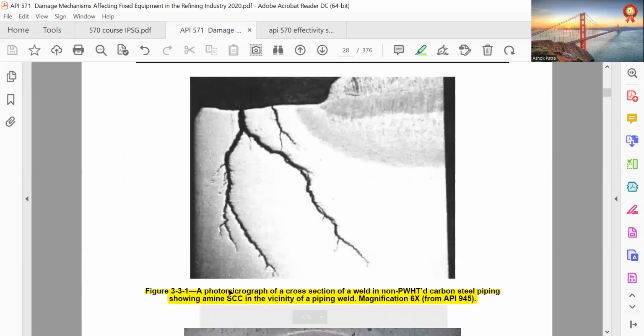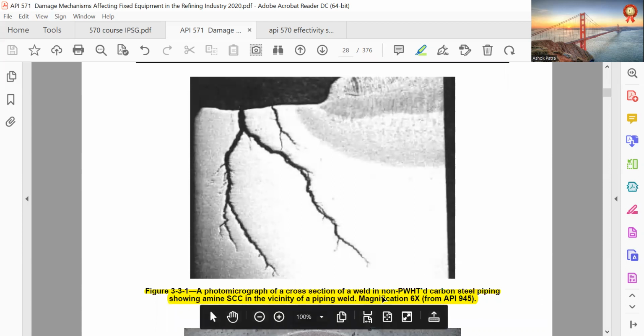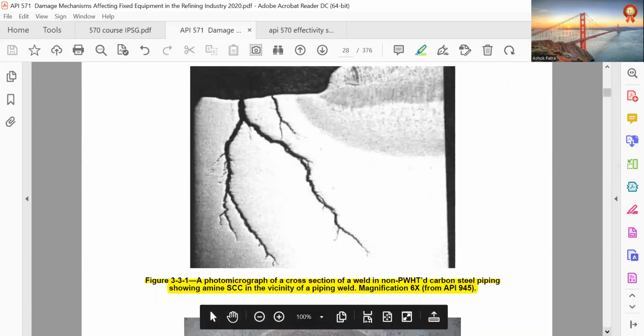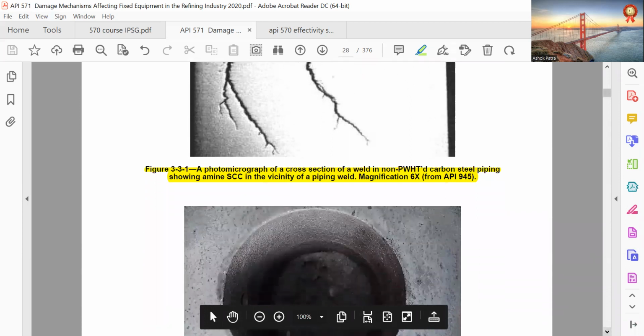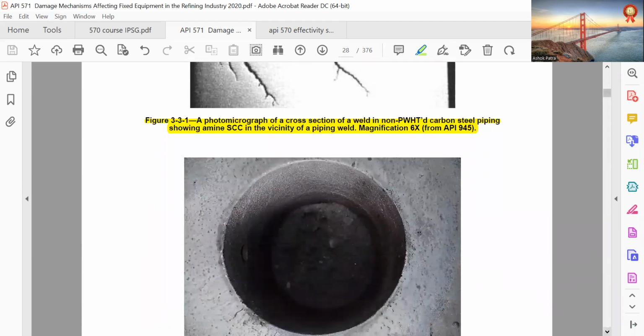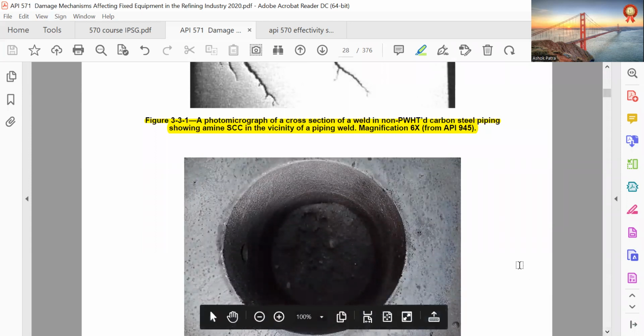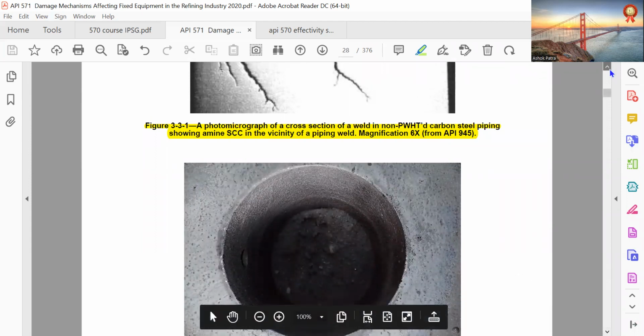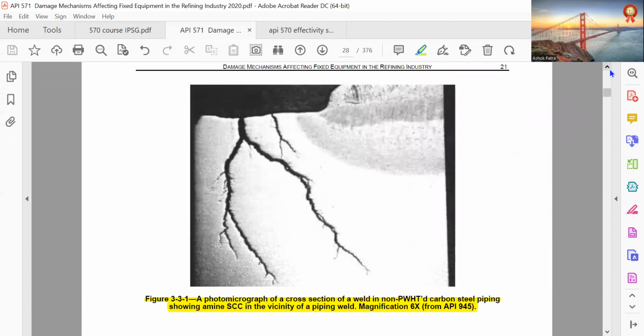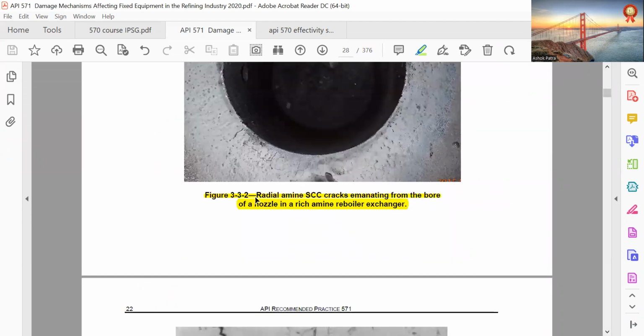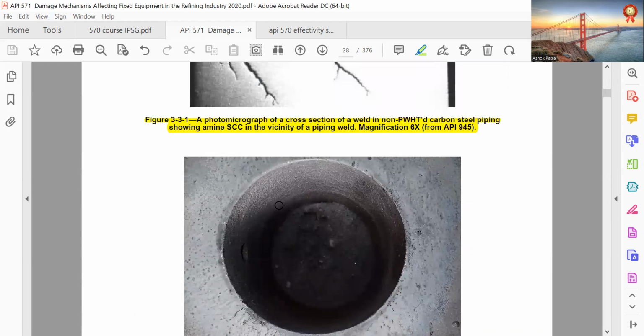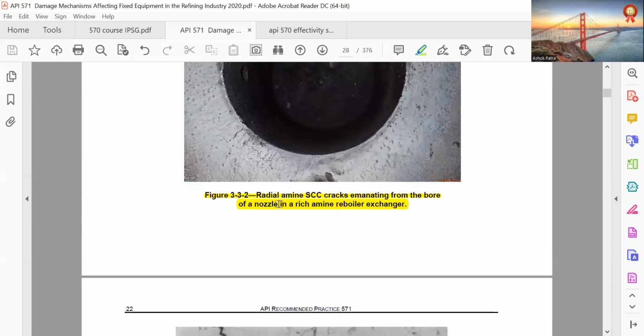There are some pictures: a photomicrograph of a cross section of a weld in non-PWHT carbon steel piping showing amine stress corrosion cracking in the vicinity of the piping weld, magnification 6x, and then radial amine SCC cracks emanating from the bore of a nozzle in a rich amine reboiler exchanger.